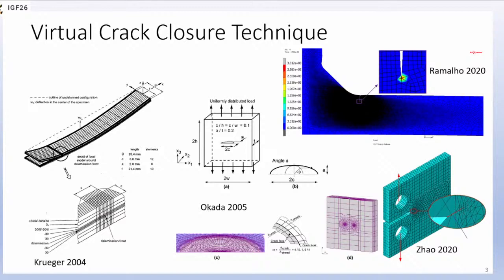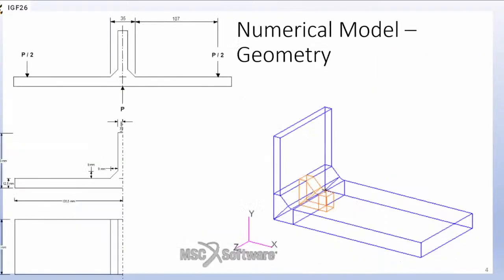It was found that the residual stress gradients in the weld toe require great refinements of the mesh, requiring large computational resources. The use of this technique in three-dimensional models appears mainly with structured meshes with hexahedral elements and in simple geometries, or in full-passing transverse cracks in simple geometries. The mesh refinement required by the numerical model limited the analysis to the central part of the welded joints, and even in these conditions, it reached the limits of the computational resources of the workstation used.